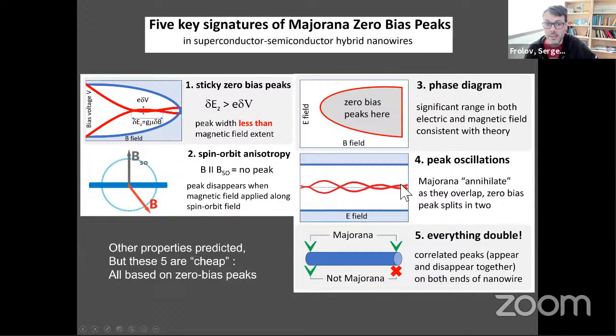Now, Majorana oscillations, we already mentioned, that's due to finite size. So when we change a gate voltage or magnetic field, the peak should come together, split in 2 peaks, come together again, split. That's when we give Majoranas more overlap or less overlap by changing parameters. A bit like RKKY or Fermi level oscillations, Fermi momentum induced oscillations. The same thing should happen here. So you want to see these oscillations and you want to relate them to your control knobs.